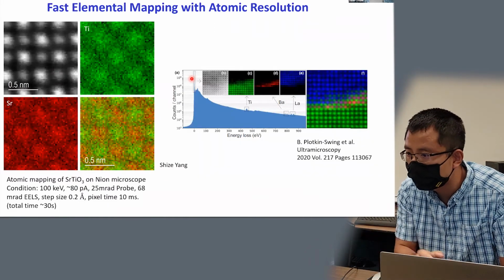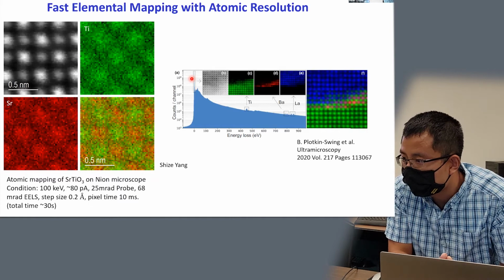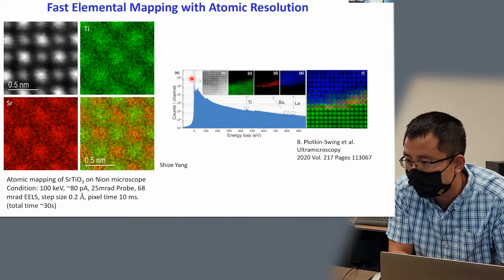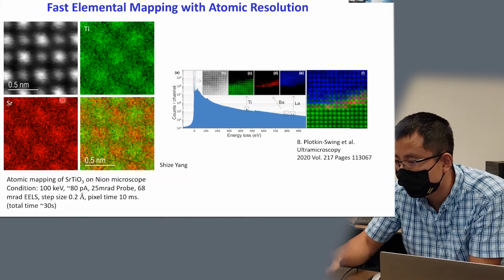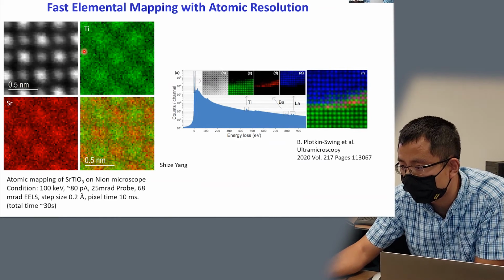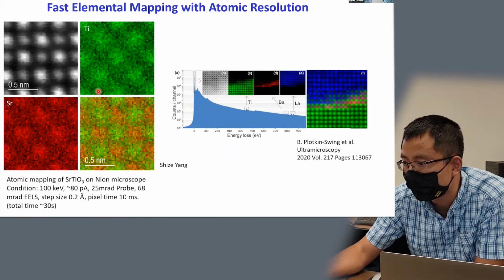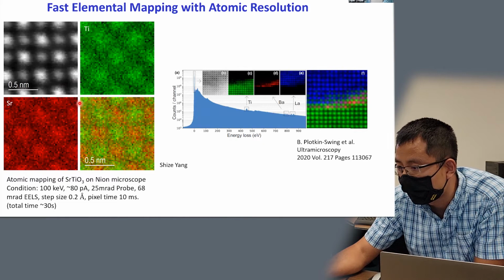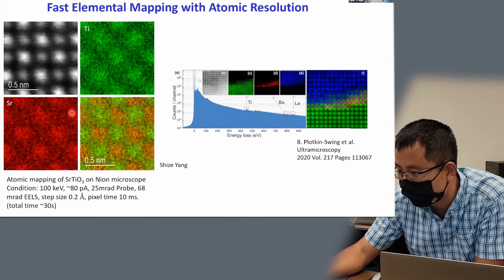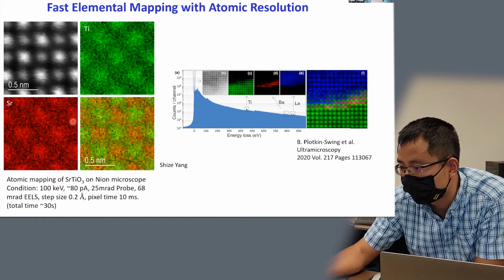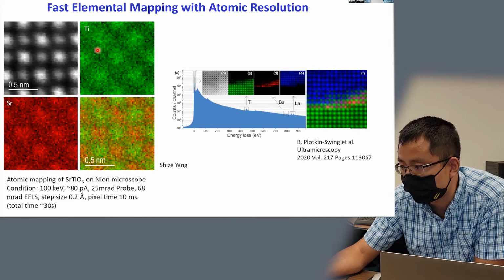Okay, here's an example about fast elemental mapping at atomic resolution. On the left side of the slide is an example that we took on the Nion microscope from a strontium titanium oxide sample. So the mapping only takes 30 seconds, and we can resolve chemical information from the strontium and titanium at atomic resolution.